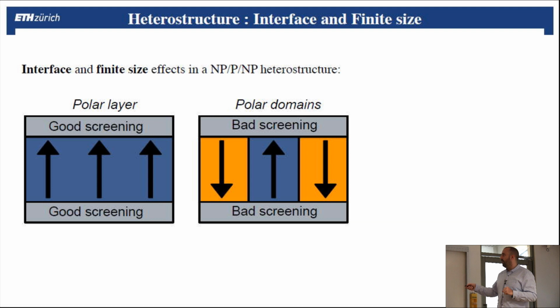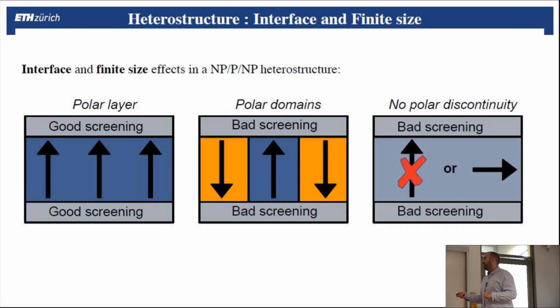But because of this discontinuity, it now has to make a balance between staying as it wanted to be and screening charges. And a way to do that is to split into these domains, because you will have a part that stays in the bulk or in the ground state, and here again, but with the opposite direction, and you don't pay anything at the interface, but you have something here that happens now.